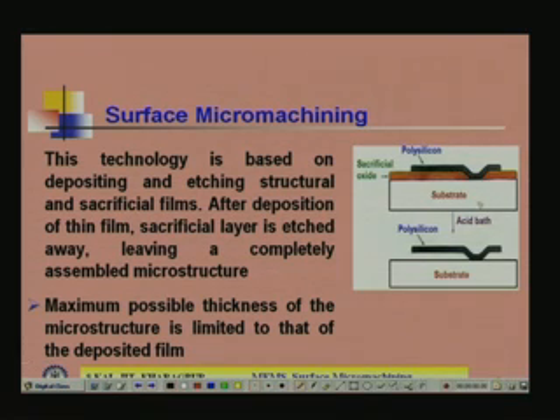So, now here this is the substrate, which may be silicon. On the silicon substrate, first the sacrificial layer, which is silicon dioxide, is either grown or deposited. Then you pattern the sacrificial oxide, that means after patterning you will get something like this. This is silicon, okay, and this is silicon dioxide that you pattern.